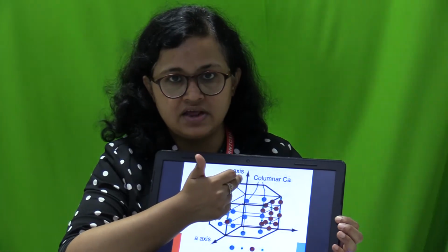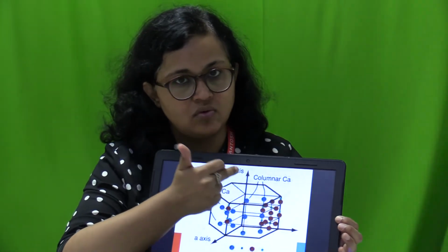These hydroxyl ions face each other and cause steric interference. When these hydroxyl ions cause steric interference, they may be shot away from the lattice structure. When they are shot away, voids result in the crystalline structure. Because of these voids, the structure of the hydroxyapatite becomes unstable. Now when fluoride is added to the hydroxyapatite, because of the similarity in size of hydroxyl ions and fluoride ions, the fluoride ions fill these voids.